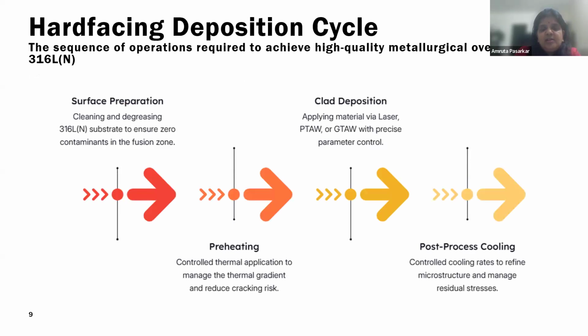Hard-facing deposition cycle. Now, how is this hard-facing basically done? First is the surface preparation, like the cleaning and degreasing of the 316LN substrate, to make sure that there are no contaminants or debris, and the surface is very clean. And then the preheating of that particular base metal is done.